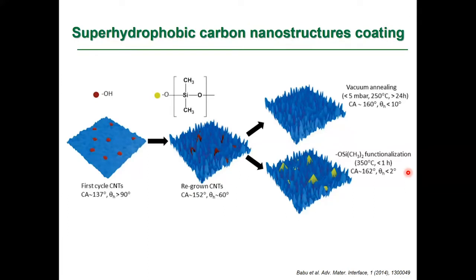But when we see superhydrophobic carbon nanostructure coatings, for carbon nanotubes or graphene, the carbon nanotube formed at high CVD conditions is itself superhydrophobic because of its excellent surface roughness and the removal of hydrophilic surface groups. And a further vacuum annealing can further enhance it. So there is no need for a low surface energy modification. But if a further low surface energy modification is applied, it will again increase the contact angle, and you can see it on 162 here and on 152 here. And it will also give extra stability to the surface.